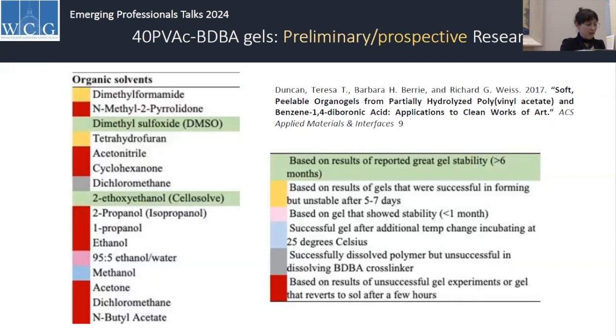So I had a look at, there is a paper, I should say a lot of the research that I'm going into, the territory I'm going into now, Teresa Duncan and Barbara Berry have done a lot of work on these materials. This is from one of their papers, and I basically looked at all of the solvents that they had put into these gel systems, and based off their results worked out what would be a viable pathway to explore going forward. And as you can see here, dimethyl sulfoxide and 2-ethoxyethanol (Cellosolve) look like they'd be promising solvents to dissolve both the BDBA crosslinker and the polyvinyl alcohol. And so I started with 2-ethoxyethanol (Cellosolve), which a few of you are familiar with, perhaps. I've never used it before, actually.